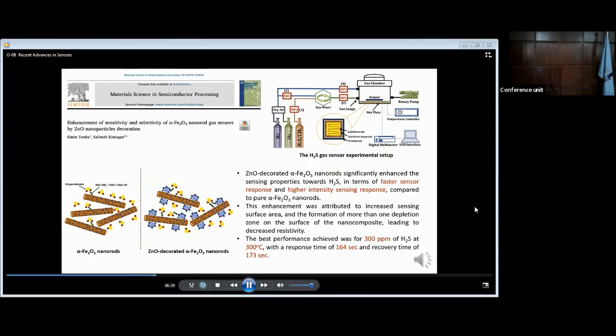As with other nanoparticles, this enhancement is attributed to the increased sensing surface area, which took advantage of the very, very small particle size of the nanoparticles and the formation of more than one depletion zone on the surface of the nanocomposite, leading to decreased resistivity. The best performance achieved was for 300 ppm of hydrogen sulfide at 300 degrees Celsius, with a response time of 164 seconds and recovery time of 173 seconds.